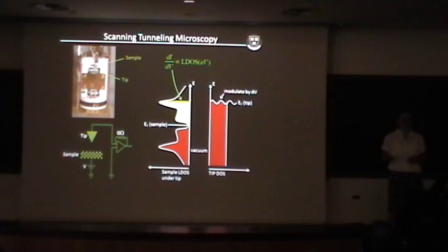And as far as your question about very, very high voltages, when you go to 1 or 2 volts, things get very delicate because, well, A, the tunneling approximation breaks down. The work function of bismuth is around 4 eV, so you're starting to get close enough to the work function that the tunneling approximation breaks down. And furthermore, you risk ripping the surface off, because BSCCO is so fragile.